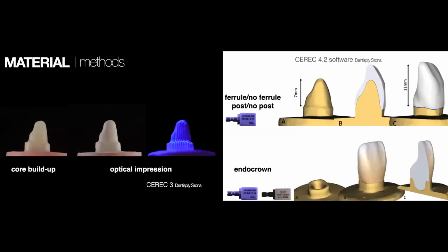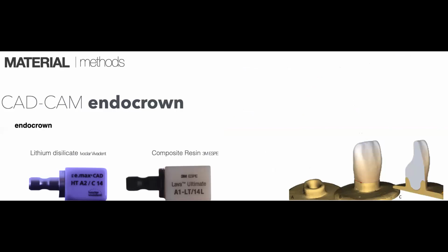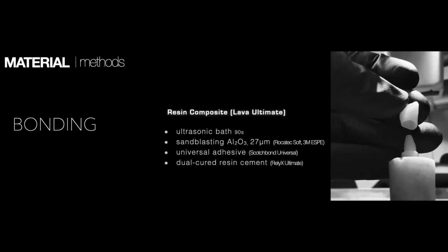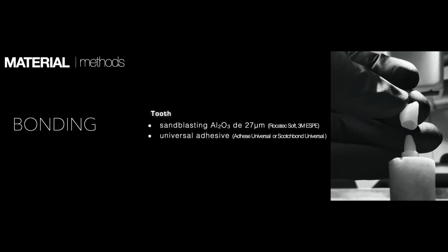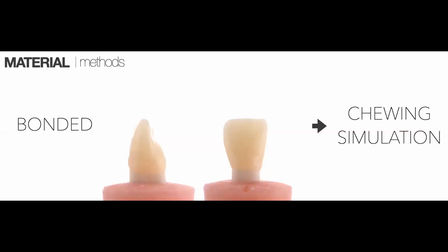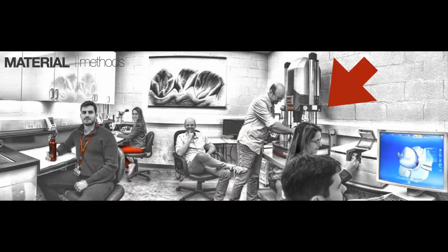And we used CAD/CAM to provide those restorations in order to make them more standard, either the crowns or the endocrowns. Everything we did was in CAD/CAM to make all the samples as close as possible. The bonding protocol we used was according to the manufacturers, either for lithium disilicate or resin composite CAD/CAM blocks. And we also did the same thing on the tooth with sandblasting and using the proper adhesive system or luting material, okay? After bonding those restorations, we went for the chewing simulation, which is the accelerated fatigue test. You guys can see on the screen Pascal's lab. We work there with CAD/CAM, providing the samples and also making all the simulations.